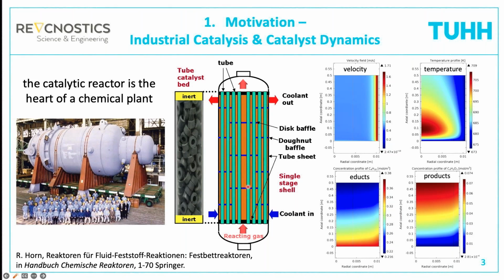And then the catalytic reactions either produce or consume heat. Here is shown an example where heat is liberated in an exothermic reaction. So we have a coolant flowing crisscross over this bank of tubes to remove the heat through the tube wall and control the temperature in the reactor. And what is now very important is that we have gradients inside this reactor. So this is a mathematical model that you see here of how it looks inside such a reactor. And what you see is there are, for example, velocity gradients. You have here a slip flow close to the wall where you have a high flow velocity because the wall is disturbing the packing in the tube. This is very normal. You have this in every fixed bed reactor.